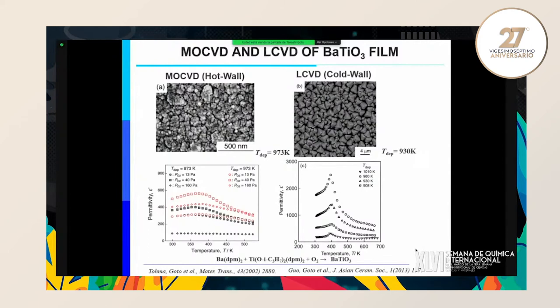Barium titanate is also very difficult to prepare by MOCVD because the precursors, barium dipivaloylmethanate and titanium isopropoxide DPM, are very reactive. Nanoparticles very easily form in the gas phase. By using common hot wall CVD, the morphology of barium titanate is cauliflower-like and agglomerated nanoparticles. The performance is not so good: low permittivity, and we can't see the transition from tetragonal ferroelectric to paraelectric cubic structure,